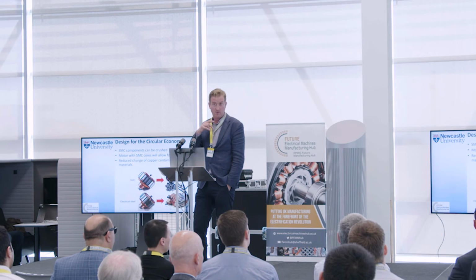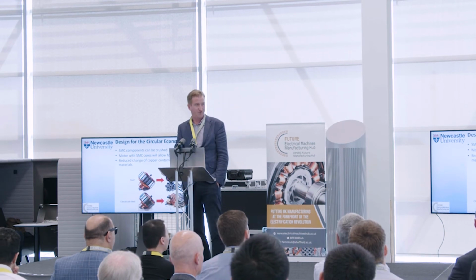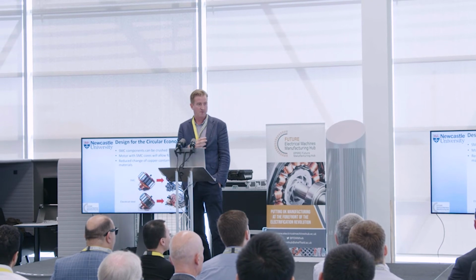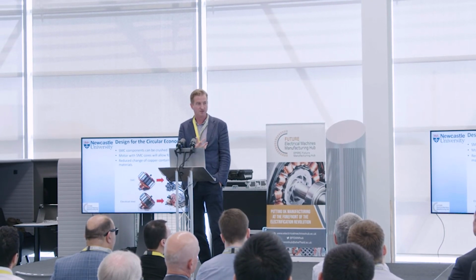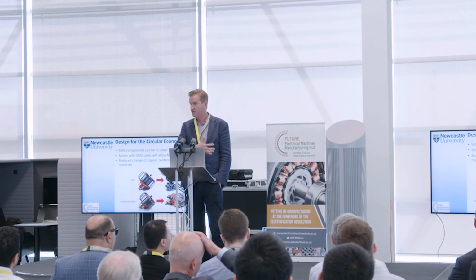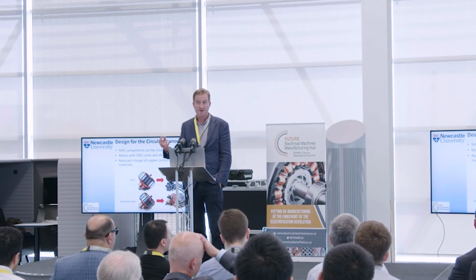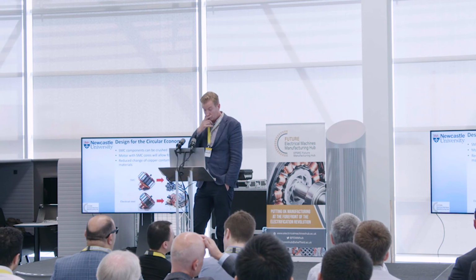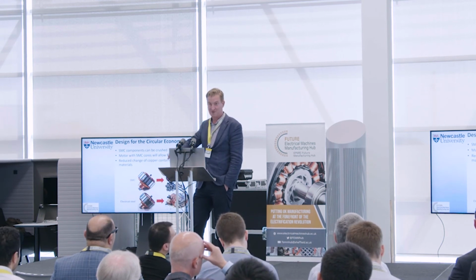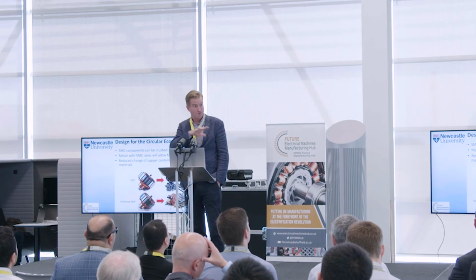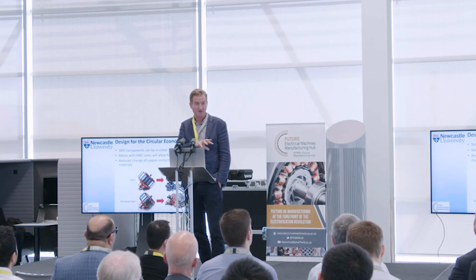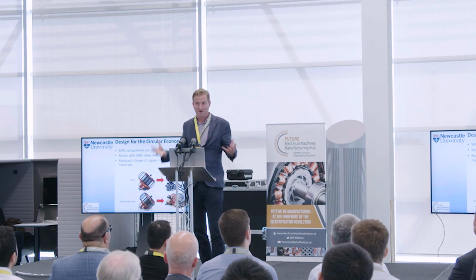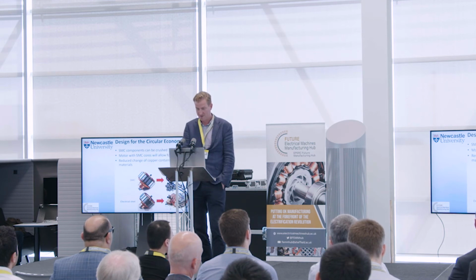One other benefit which has always been around but is becoming more of interest is the use of the material in the circular economy. If you take a laminated machine and want to recycle it, you've got to remove the copper completely, otherwise it pollutes the steel when that's recycled. You get copper in there, it's useless. So it's quite difficult to get the copper off. You've got to manually cut it, attack it with an angle grinder or whatever. The soft magnetic composite is a fairly brittle material. So if you took the machine and squashed it, the iron powder would separate away and you would be left with the copper. So there are potential benefits there. It's easier to break.